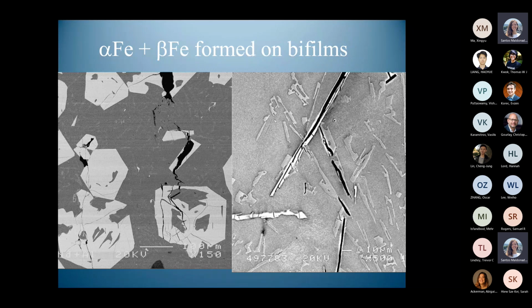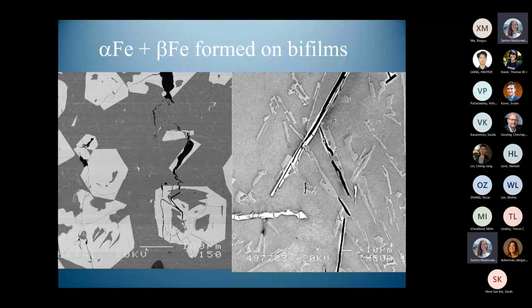And here's another instance of the way the structure of inclusions relates to the bifilm. And in every case, in fact, every time I've ever looked into any inclusion or second phase, it always nucleates and grows on a bifilm. Now, at some stage someone is going to find an inclusion or a second phase that doesn't nucleate on bifilms, but I haven't found one yet. But maybe they do exist somewhere. But here, they certainly nucleate and grow on bifilms.